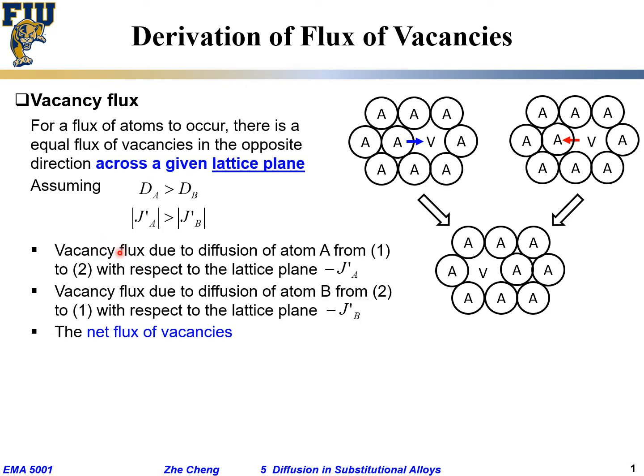So then we would think, okay, for A atom to move from 1 to 2, it would create an effective vacancy flux. A atom moves, that will create an effective vacancy flux, JA prime, but minus. JA prime means what? JA means flux of A atom. Prime means it's with respect to my so-called chosen lattice plane. Okay. A atom moving towards right. At the same time, I would have an equal value but opposite direction of a vacancy going backward for A atom motion.